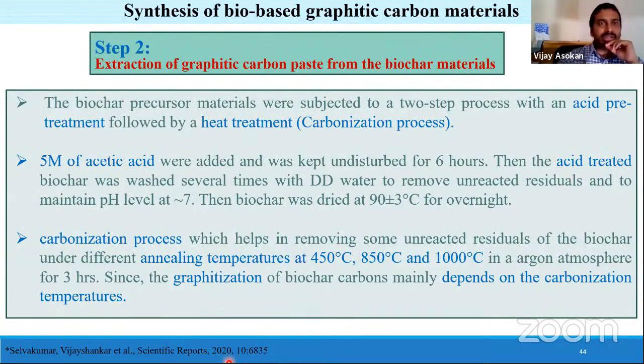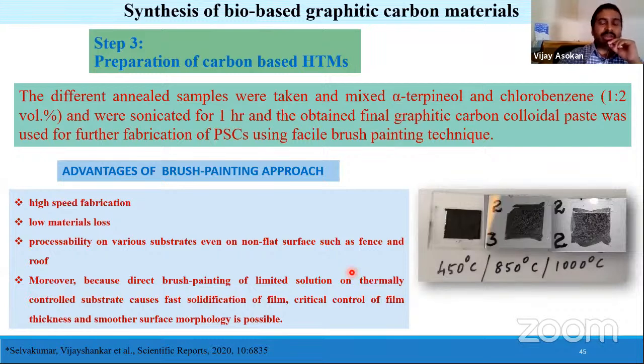From the first step, we are now moving to the second step. Here we use the extraction of graphitic carbon paste from the biochar materials. We used a biochar precursor material subjected to a two-step process, with an acid pre-treatment followed by heat treatment. So we make a carbonization process here, trying to graphitize it with the parameters given here. These were clearly noted in our paper. We used different annealing temperatures, 450, 850, and 1000, to understand the graphitization process and the influence of such differently graphitized material on the efficiency parameters. And the third step is preparation of carbon-based HTMs.